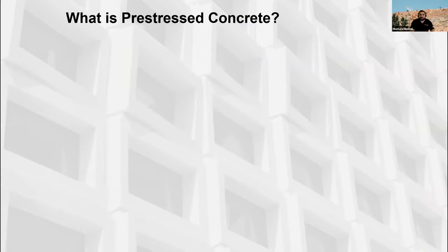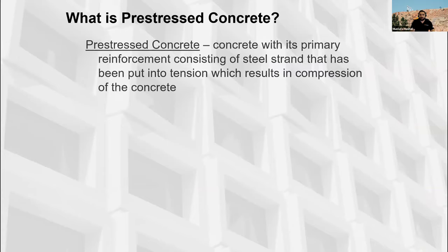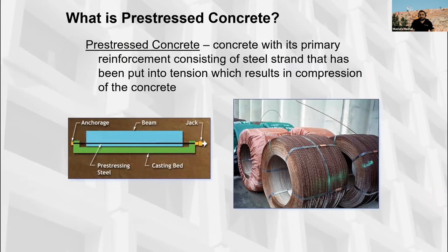So what is prestressed concrete? Well, as you know, concrete is strong in compression but weak in tension. It's about 1/10 of its compression strength in tension. That's why we have to put reinforcing in concrete. Prestressing is basically a method of reinforcement where high strength steel strand is pulled into tension and then the tensile stress is released into the concrete after the concrete has reached the necessary compressive strength. It depends how much tension you put in those strands. That's the design process. Normally for 1/2 inch diameter strands, the force is between 20,000 to 30,000 pounds.